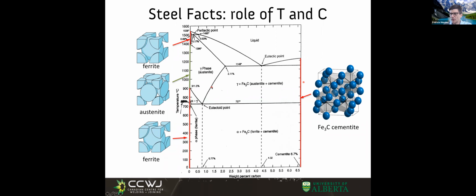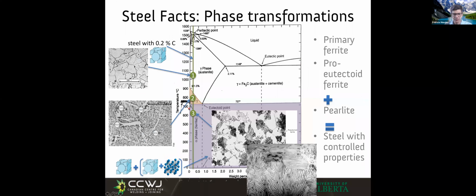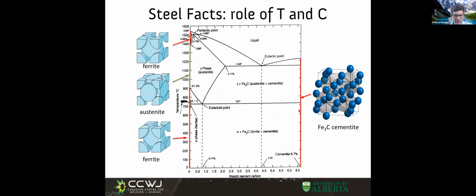There's one especially interesting point called the eutectoid point, at a composition of 0.77% carbon—this is roughly the composition of train wheels or railroad tracks. As we cool down we're in the single phase of austenite, and when we cross this point, all of a sudden we get ferrite, which can take very little carbon, along with cementite. Those two are mixed, and what comes out has one of these mineralogic names: pearlite.